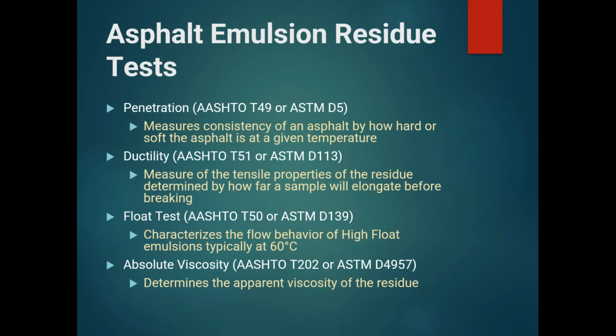Float test is an interesting test because it's a residue performance test, but it's also a little bit of a characterization test. There's a category of emulsions called high float emulsions, and so this float test characterizes the flow behavior of high float emulsions, typically at 60 degrees C. So if you have a high float emulsion, this will typically be part of the specification to test and ensure that it does actually meet the high float requirements. And then also absolute viscosity, and that determines the apparent viscosity of the residue itself.